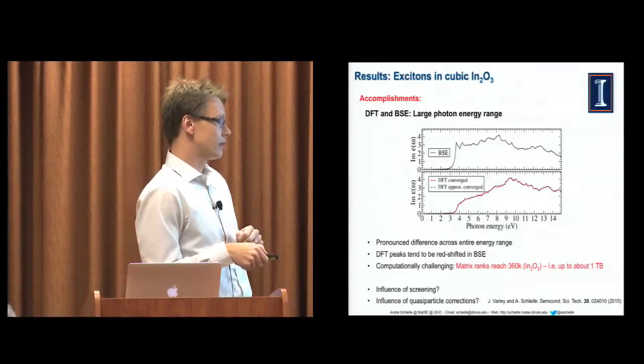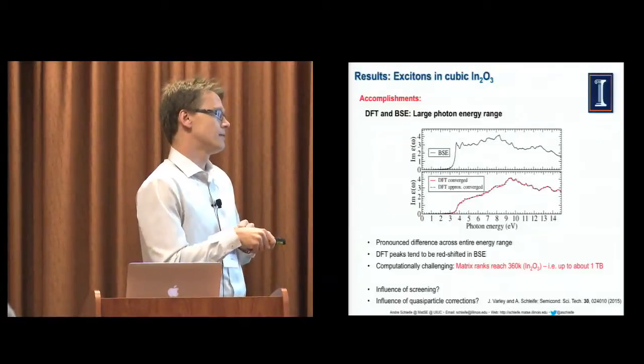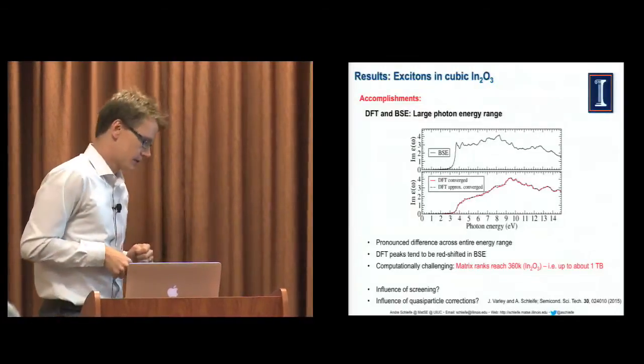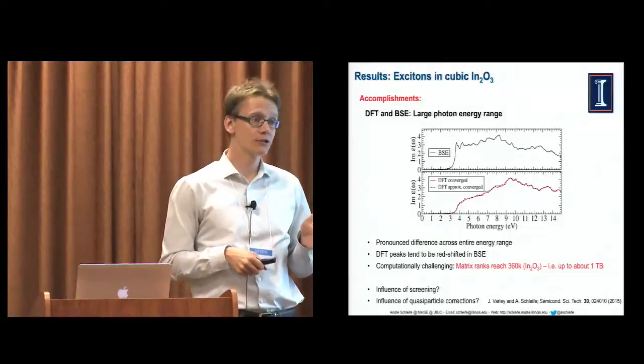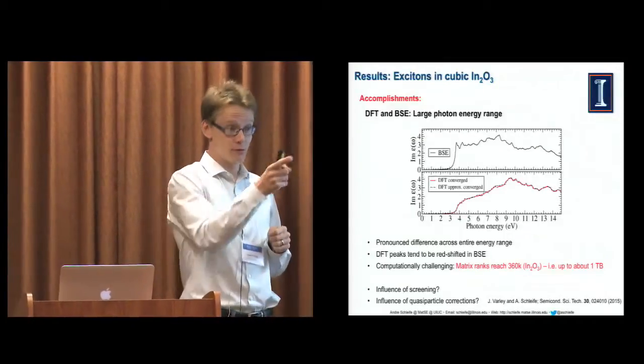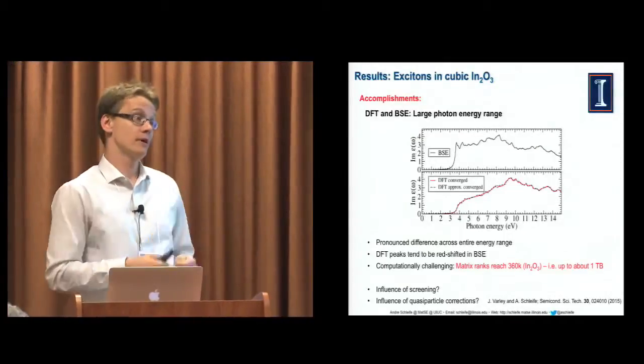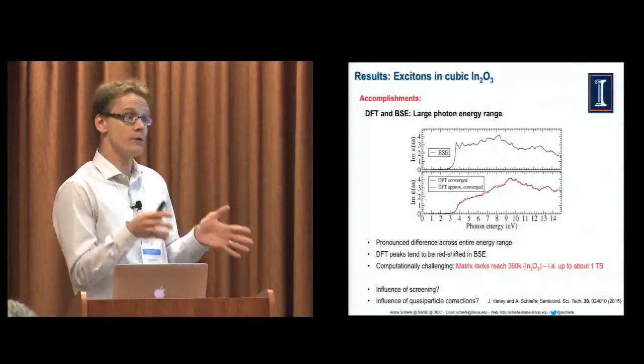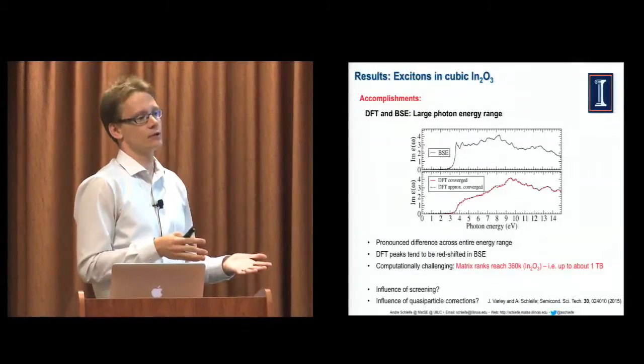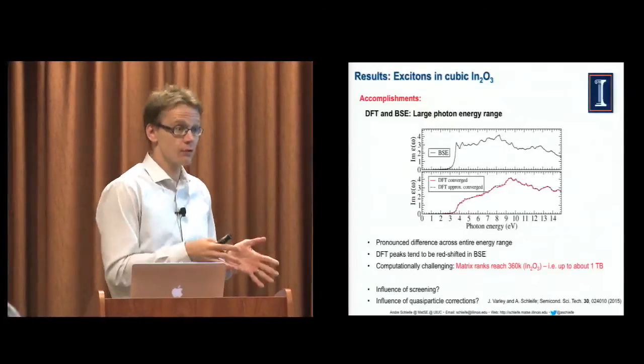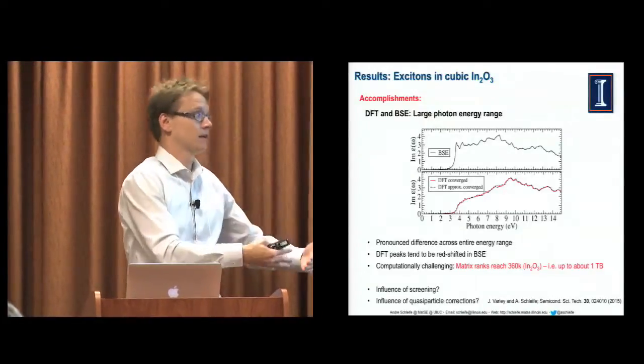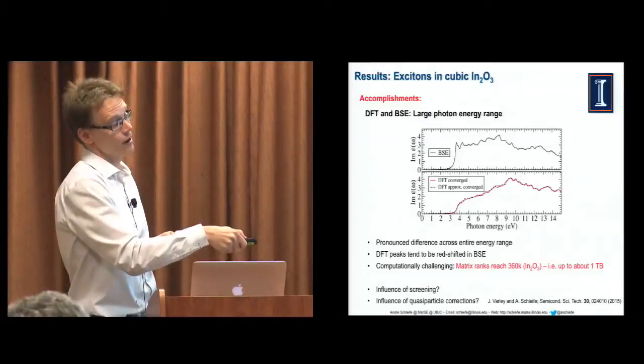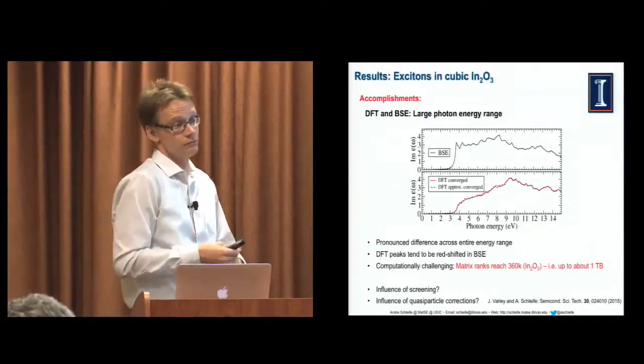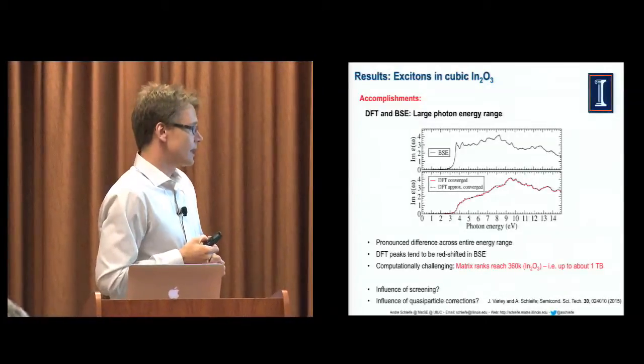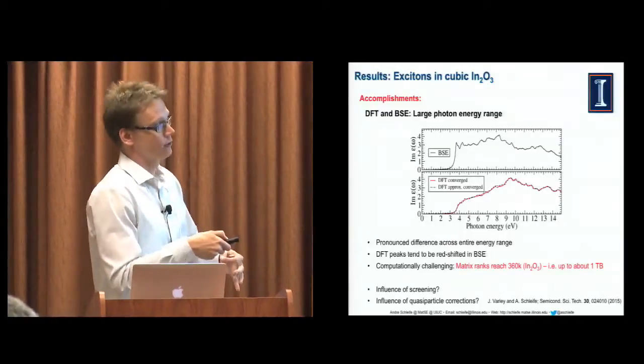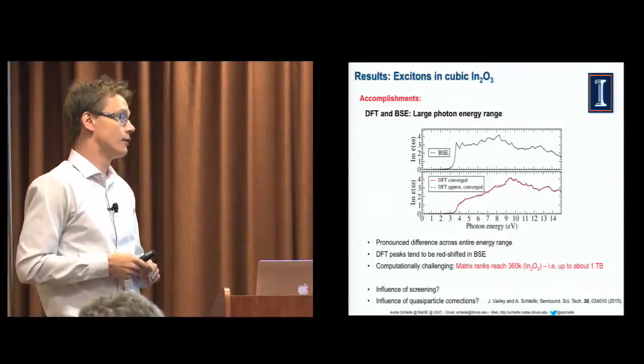One example for a calculation of this one, when we read this matrix, it takes, if I remember correctly, on the order of 8 hours to just read this matrix into memory. Actually, we're now trying to speed this up because that becomes a limiting factor. Before we used Blue Waters, that was not the case, right? The reading step was much faster simply because the matrices were much smaller. But now that we actually can get to these large photon energy ranges, we start running into these kinds of problems. So we have to deal with those now. Nevertheless, Blue Waters allows us to even do these calculations. That is something that we could not do on a different machine.